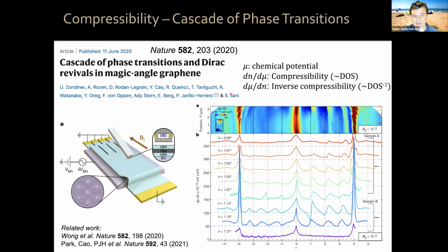So in the group of Shahal Ilani, they have developed this very interesting technique where you have a carbon nanotube, which acts as a single electron transistor. They have it at the tip of essentially an atomic force microscope. And then they can scan with this tip across the device, and they can measure locally the chemical potential, okay?